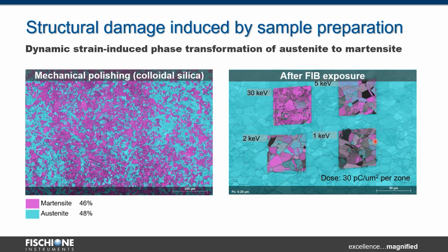This slide illustrates how sample preparation can alter the material microstructure. As you can see here in the austenitic steel example, we observe a strain-induced phase transformation of austenite to martensite. The martensite is in the pink color here. And this is induced by mechanical polishing or by FIB bombardment of the surface, as you can see here, even at low energy, as low as 1 kiloelectron volt.